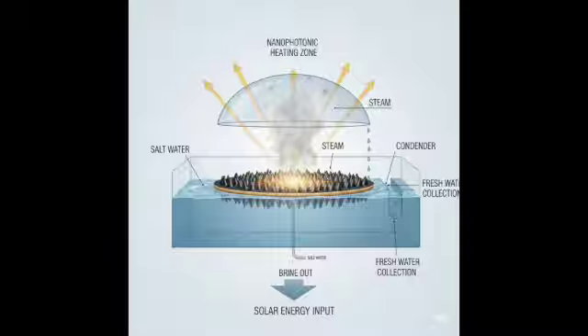That's the major drawback. Because the filler is distributed throughout the entire membrane thickness, a large portion of it is buried deep within the structure, far from the surface. Where it can't actually absorb sunlight or contribute to surface heating. Exactly. So you end up needing a much higher overall concentration, a larger volume of potentially expensive photothermal material compared to just applying it to the surface. Much of it is effectively wasted from a photothermal perspective.